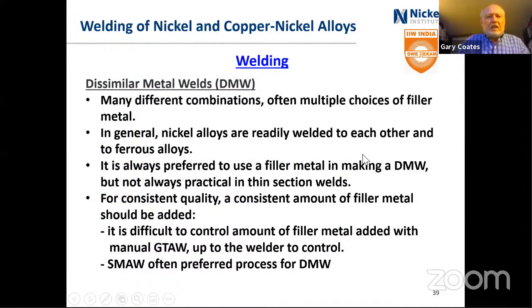I don't want to talk a lot about dissimilar metal welds, but often there are multiple choices of filler metals available that you can use for them. You have to really look at what the two different metals are, what the tolerance for the metals are. We saw that with the high copper alloys, they didn't have a tolerance for iron. Some, like the B alloy with the high molybdenum, doesn't have a tolerance for other things. So you really have to look at the particular combination. In general, they are relatively easy to weld with each other.